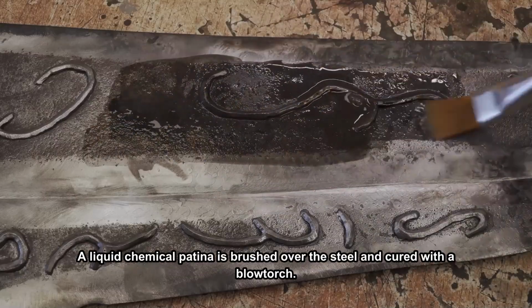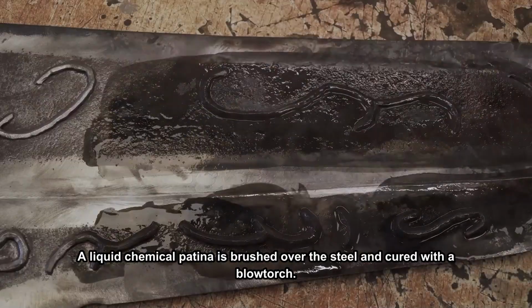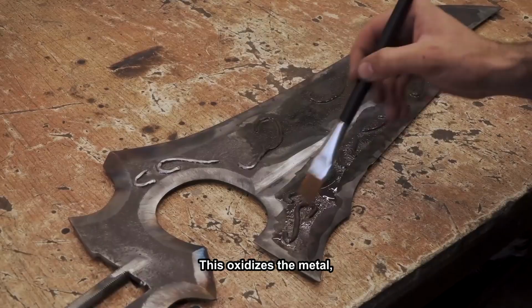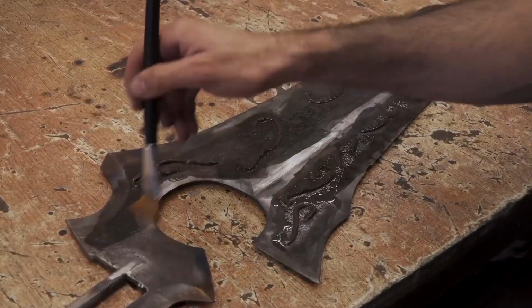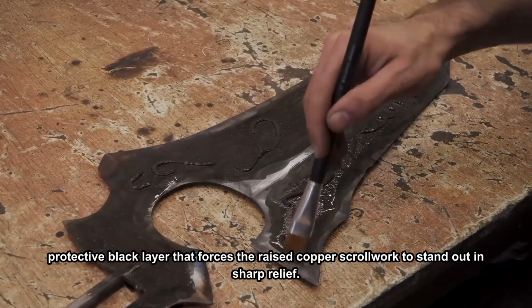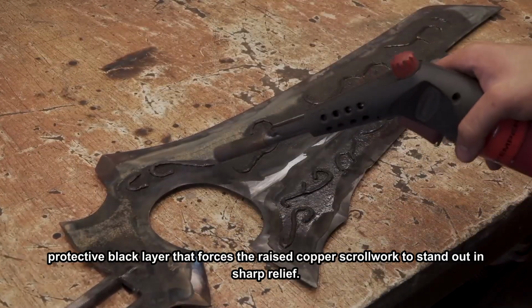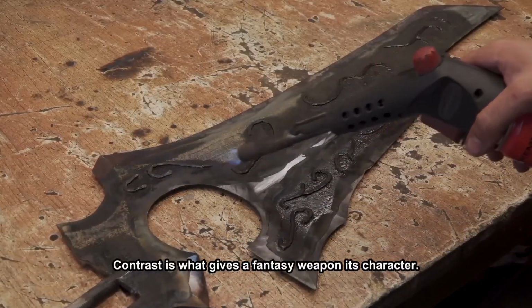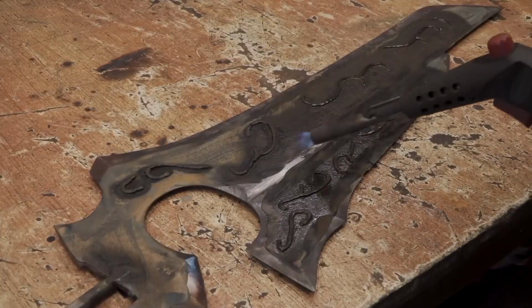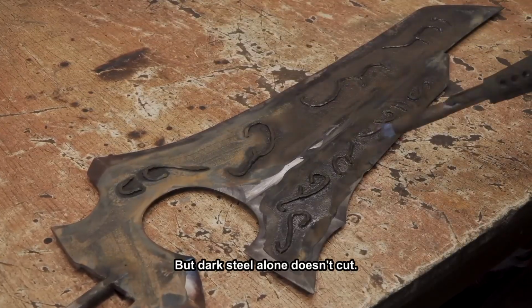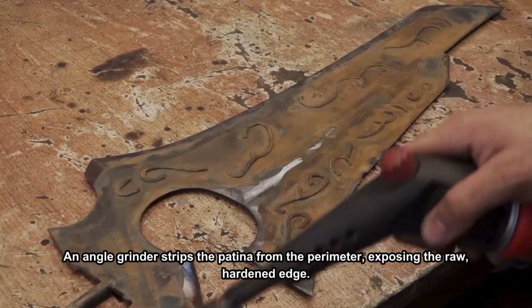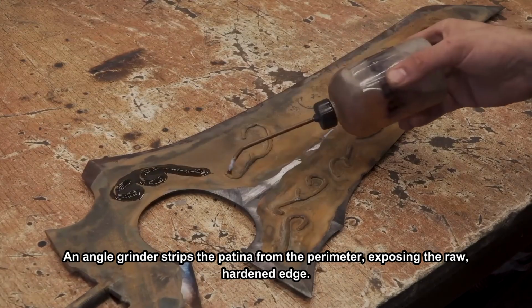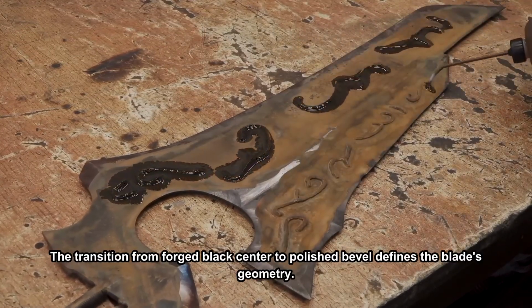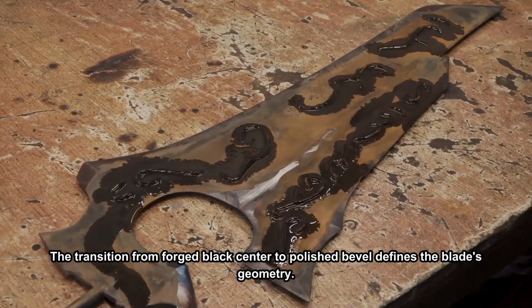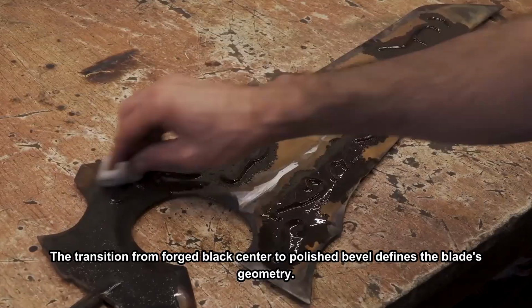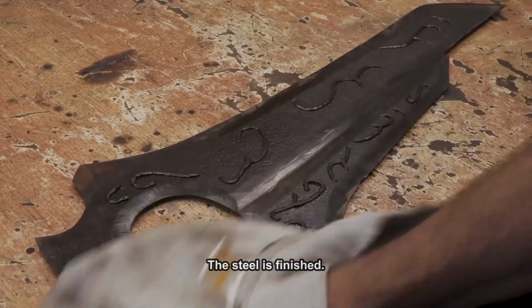A liquid chemical patina is brushed over the steel and cured with a blowtorch. This oxidizes the metal, creating a deep, protective black layer that forces the raised copper scrollwork to stand out in sharp relief. Contrast is what gives a fantasy weapon its character. But dark steel alone doesn't cut. An angle grinder strips the patina from the perimeter, exposing the raw, hardened edge. The transition from forged black center to polished bevel defines the blade's geometry. The steel is finished.